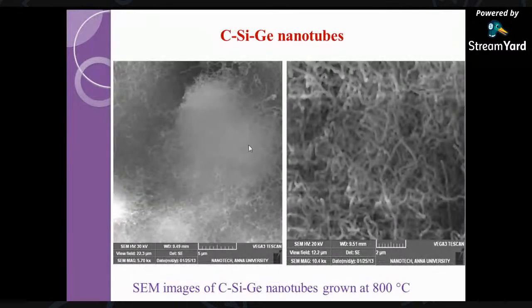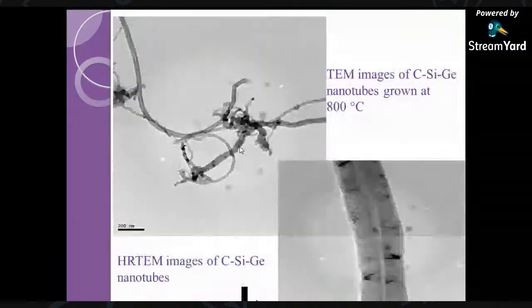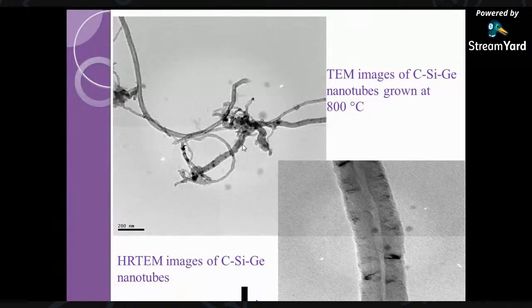Okay, so this is the image. You can see that it is formed at 800 degrees centigrade. These are the carbon, silicon, germanium nanotubes that you can see, which form in a huge quantity. Okay, it gives a good yield. And this is the TEM image, which clearly indicates that it forms long tubes, and it has a hollow structure, which is one of the remarkable findings.